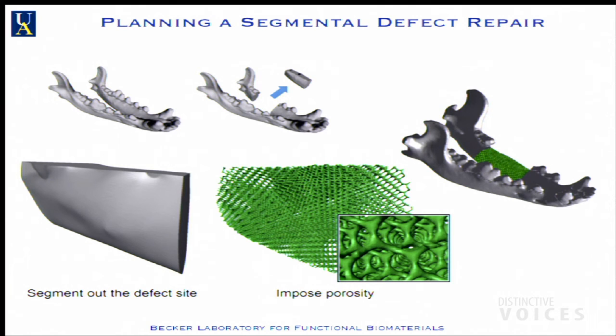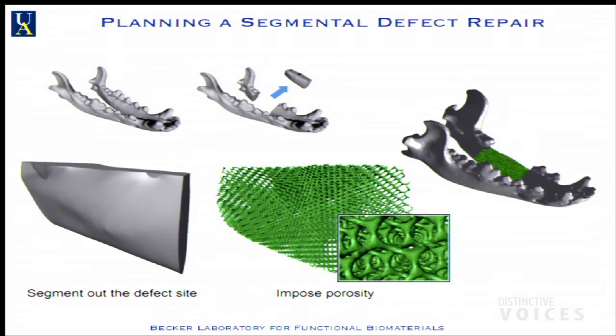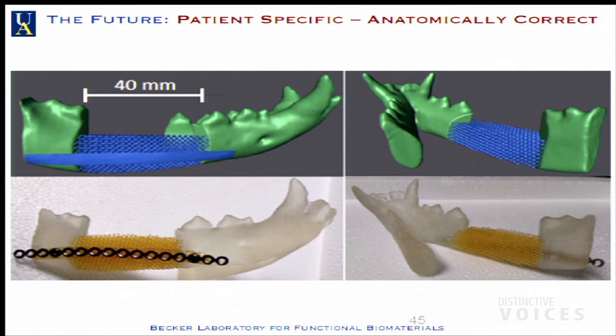Now this is our early structure, right? So it's basically a homogeneous gyroid, which again is the most mechanically robust. But you can imagine that if you can control anisotropic or complex patterns, you might be able to have areas where the outside of this structure would grow faster than the inside. Or based on the stress patterns, you might have struts in here that weren't homogeneous like the gyroid. So there's the in silico design, and I can tell you that this actually does work.